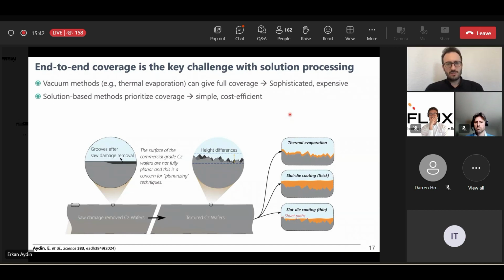If you want to fabricate the perovskite on such layers, the problem is that you have to make good coverage on these pyramids. You shouldn't have any open pyramids, because basically they will be touching your front TCO and causing a shunt. So vacuum techniques are pretty good for this, but so far the vacuum-based techniques are not as efficient as the solution-based techniques. But with solution-based techniques, spin coating, slot die coating, we have to really levelize the perovskite to make sure that none of these pyramids are coming out.